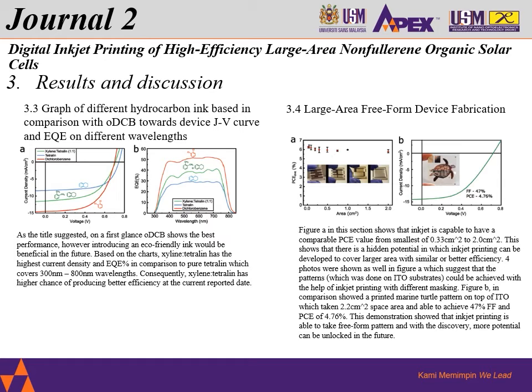So you can see over here, ODCB obviously has the highest efficiency and the highest current density, but it is followed by xylene tetraline, in comparison with the pure tetraline. So you can see that between these two eco-friendly based inks, you can go for xylene tetraline since it gives higher EQE and higher current density.